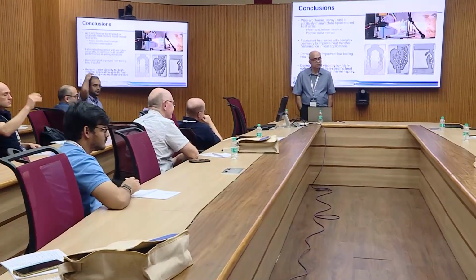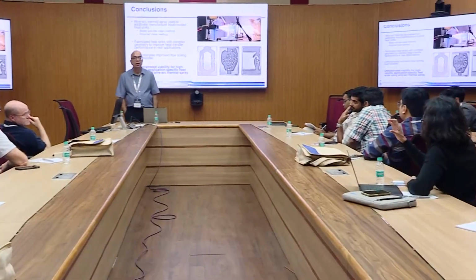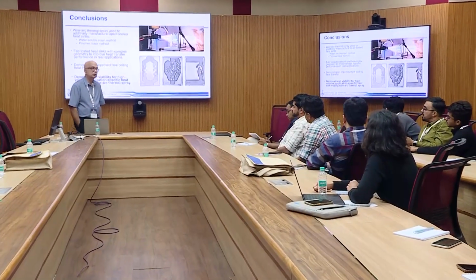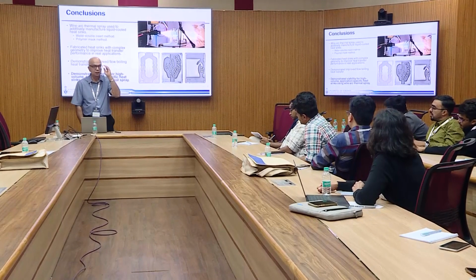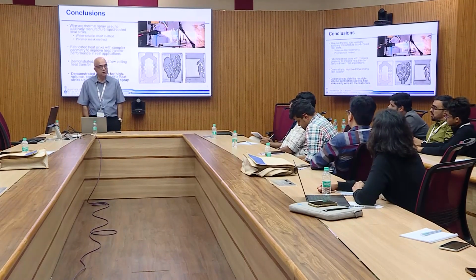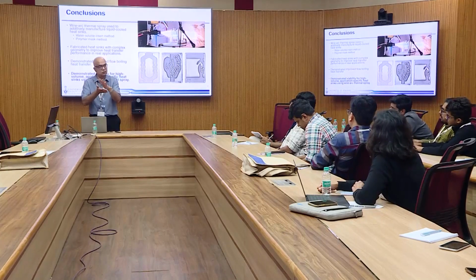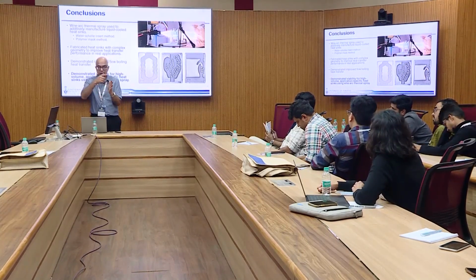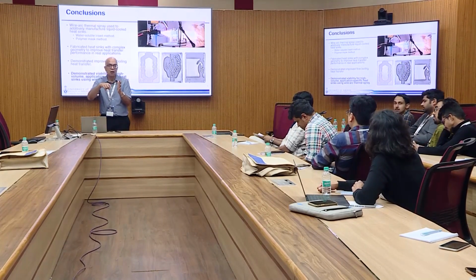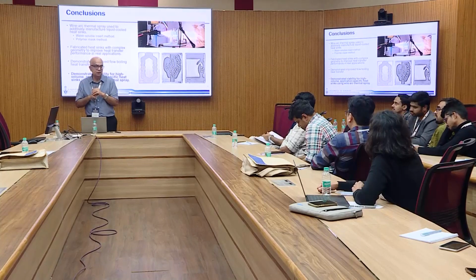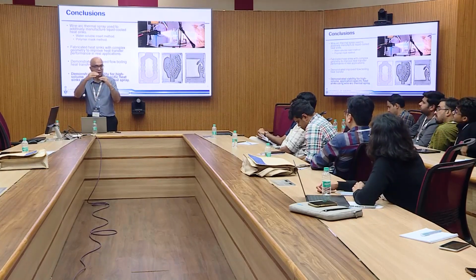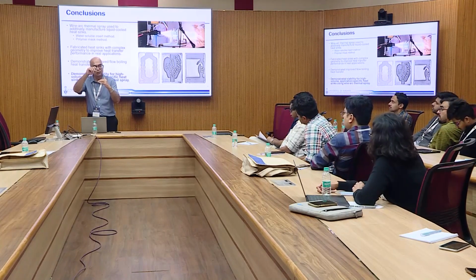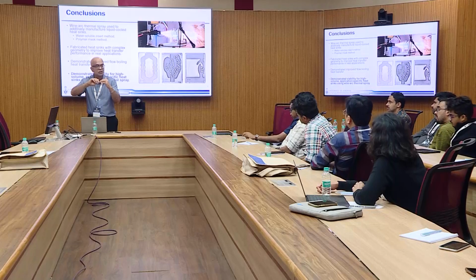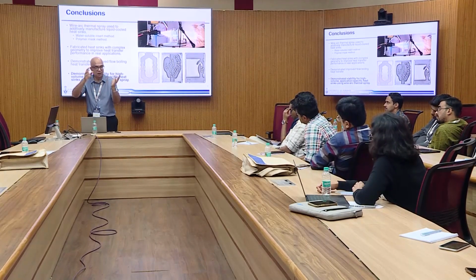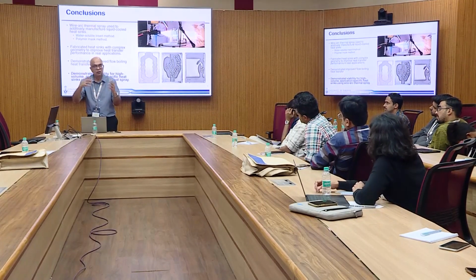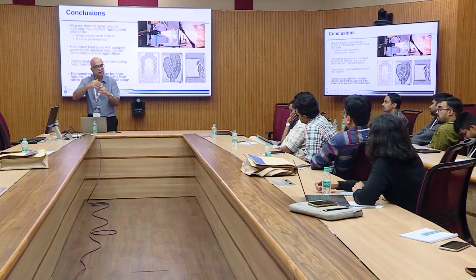Yeah. What is the thermal conductivity of this sprayed block technique? Yeah, so the thermal conductivity of these is less than the bulk material, and it can be as low as about half of the bulk material, because they are splats which are bonded together, and you actually get oxide at that interface. It's actually not that serious a concern in this application, because if you look at the thermal resistances, your convective resistance is about an order of magnitude higher than your conductive resistance. So even if your conductive resistance increases by a factor of 2 or something like that, overall it's still negligible. It's all about the convective resistance.